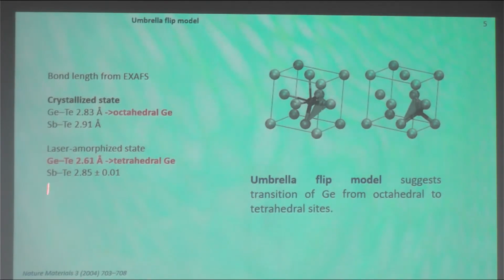Here they studied the bond lengths in the crystalline state and in the laser amorphized state. They used real optical devices, I think DVD-RW, and they looked at the bonds between germanium telluride and antimony telluride, the bond lengths. We know that in the crystalline state such bonds also exist. What they found is that in the laser amorphized state there are two types of bonds, germanium telluride and antimony telluride. The antimony telluride bonds are a little bit longer compared to the germanium telluride bonds.